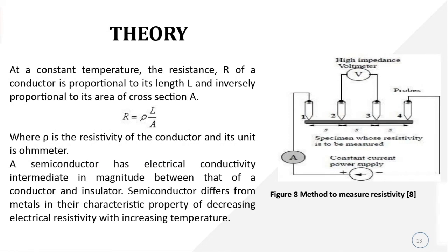We have to increase the temperature of the sample, and we are using four probes for connecting our sample. You can see here, this is the sample that we are using, in the form of a thin wafer. Four probes are connected to this semiconductor material. The two outer probes we use to measure current, and the inner probes we use to measure voltage. And this is the schematic diagram that we are using for this four probe setup.